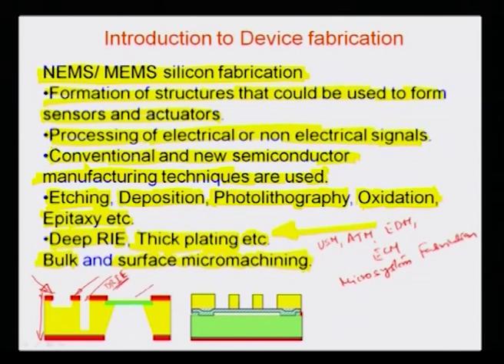The third example as illustrated here is again a very interesting example where there is a P double plus layer which has been impregnated here using an implantation or some doping technique, and then there is an anisotropic etch which actually goes on from the backside here, and the material is selective to only silicon and not to P double plus. So, whenever the etchant comes and hits this area, it leaves a thin membrane here, because it is not able to etch this part. It is selective to P double plus, as I already mentioned, and the remaining silicon is etched away. So, this is another way of getting thin film pressure sensors. And this is also known as bulk micro machined pressure sensors.